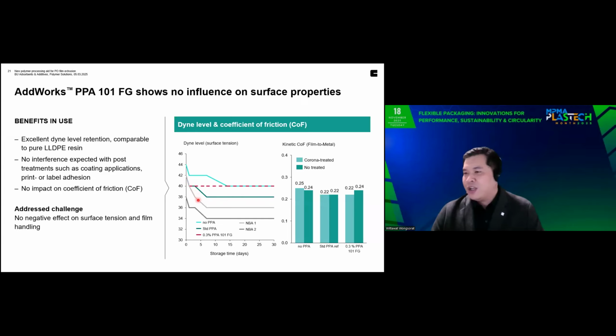For the lower two lines, the siloxane PPA and the modified silicone PPA, they also achieve a dyne level of 42 in the beginning, but after that it drops significantly to 36 and stays at 36 until 1 month. For another modified silicone substance, after adding it you can see it achieves a dyne level of 38 and lowers to 34 until 1 month.